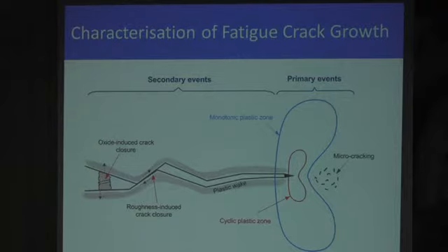In fact, here I showed that during the normal fatigue cycle, the crack actually closed almost all the way until the peak load, just by different percentages. So essentially, by and large, the crack is closed during a normal constant amplitude fatigue cycle.